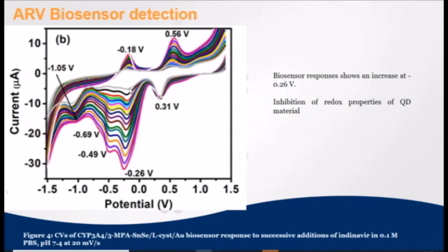So why is this graph different from the other graphs? This graph is different because now we are detecting our ARV drug. In this case, we are adding different concentrations of the ARV drug. You can see that we have added more than 15 concentrations. It is very important to add from 10 up to 20 because we need to get a longer linear range, and also the sensitivity and our limit of detection from that linear regression.